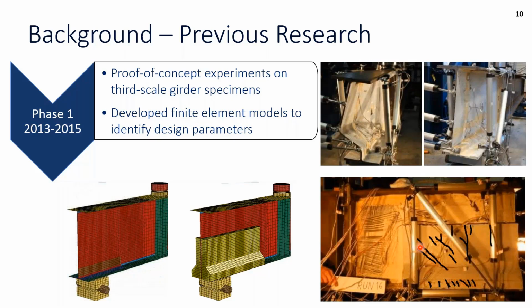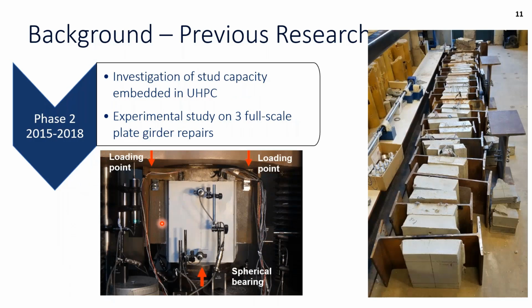So there were third scale girder specimens, and here you could see two of them. This is the intact beam. This is the beam with simulated corrosion damage, and you can see we get that crippling at the bottom. And then we had one test of a partial height UHPC encasement. And what we were able to show here is that the beam not only didn't experience any buckling at the end, we were able to get a strength above that intact state. And another key part of that project was looking at our finite element modeling to determine what are those really specific design parameters that we have to look into further. And that led to phase 2.